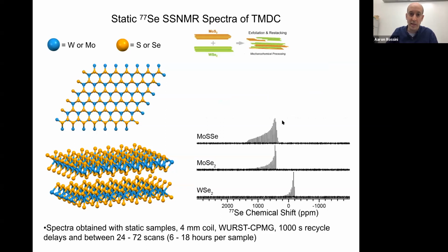Okay, what happens if we look at a ball milled sample? This is molybdenum sulfide selenide that was made by ball milling molybdenum sulfide and molybdenum selenide. As we maybe expect, we don't see much broadening of our selenium spectrum since we're just going to be substituting in some sulfides into the selenium positions. That maybe is going to have a minimal effect on the selenium NMR chemical shifts.